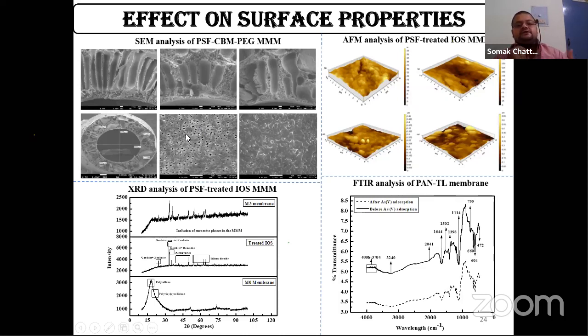So therefore, in this case, what we learned is that across the cross-section of the membrane, there is a delayed demixing process. And because of this delayed demixing process, the macrovoid structures, which were initially elongated in length, increased their length while they reduced their breadth, and therefore the number of macrovoids was also reduced. But on the top surface, we were able to see that once the additive concentration increased, the instantaneous demixing was restricted, and therefore the top pores were restricted with the different types of inorganics that we were impregnating in the membrane.